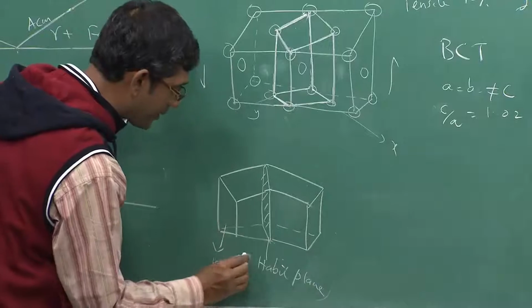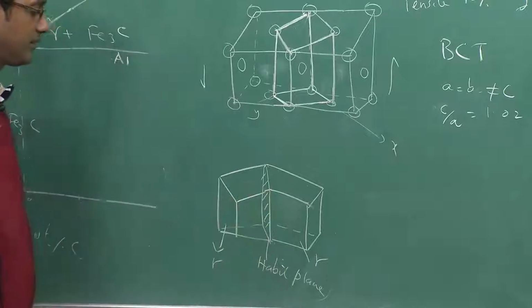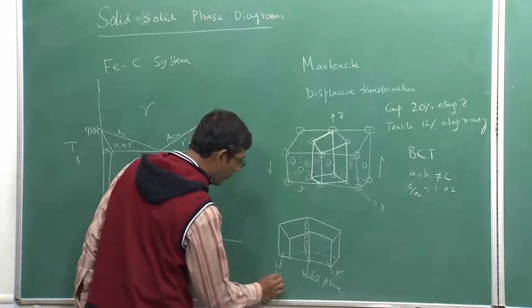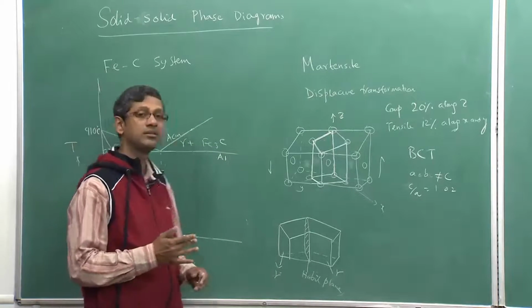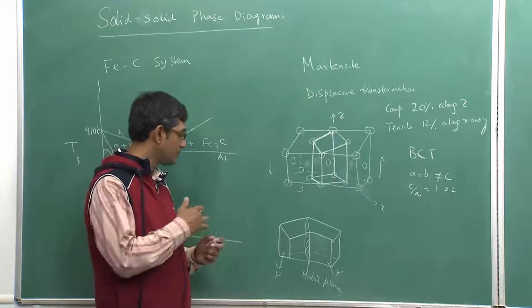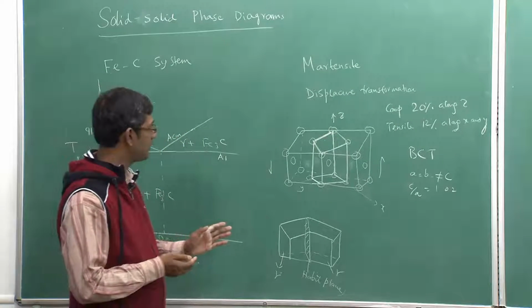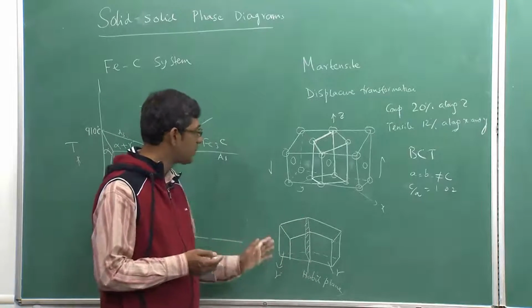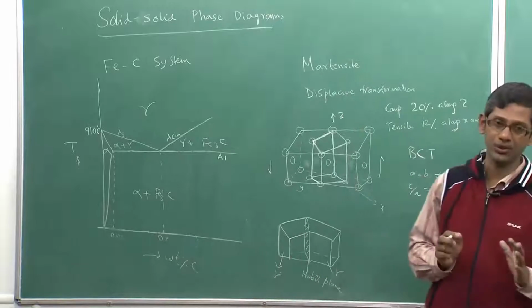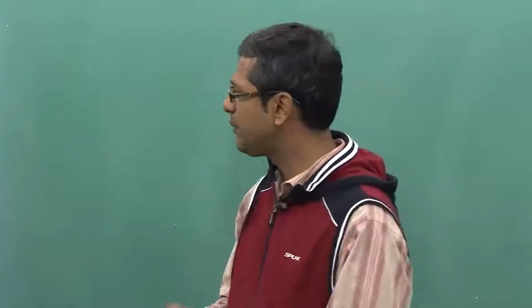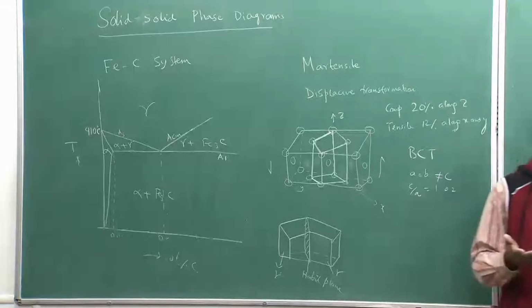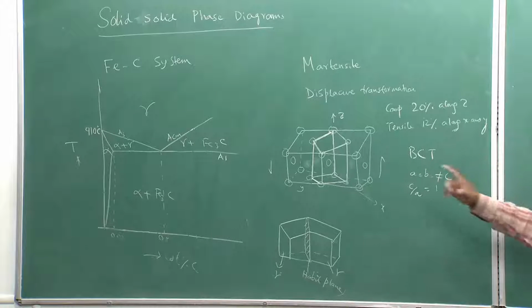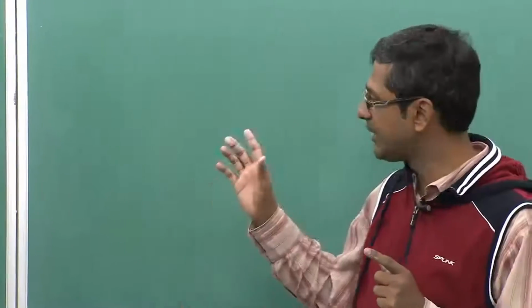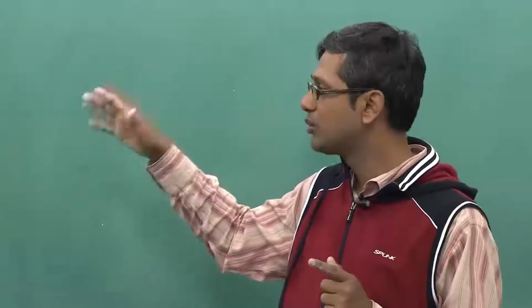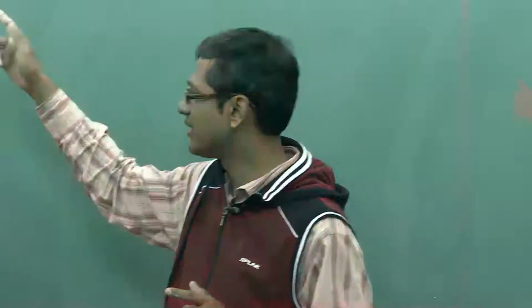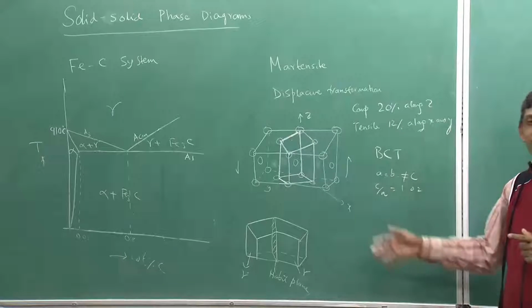This is gamma, untransformed gamma, this is also untransformed gamma, and this is the Martensite. So in the Martensite, one of the planes will remain undistorted, with no change of shape or position, and that is what is known as the habit plane. This plane does not undergo any kind of distortion. In order to keep this plane undistorted, you need certain deformation to happen, because you are already deforming the whole crystal. You are changing the shape of the crystal from FCC to BCT, and within this Martensite, one of the planes remains undistorted.